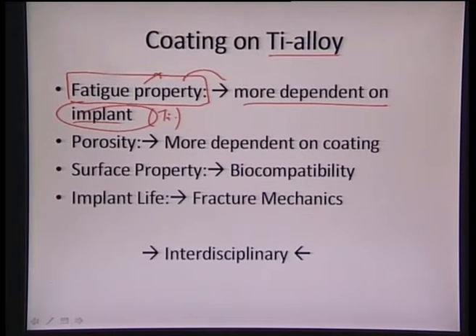And secondly, there is one more term called porosity, and it is more dependent on the coating part, because porosity essentially decides the manner in which the surrounding environment of the body will interact with the implant material. If our coating itself is bad, if the coating is not good, not adhering to the cells, cells may not tend to adhere on the implant and we will see a failure, or there won't be any bonding between the implant and the surrounding bone and tissues.